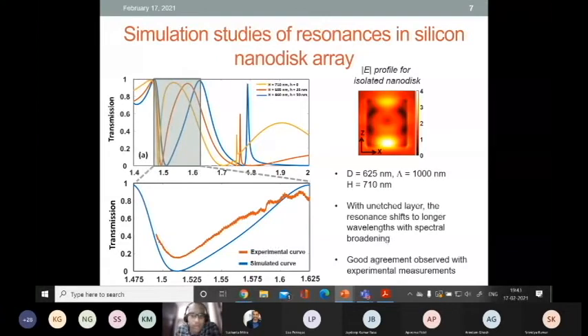This is a particular metasurface we designed, and we intentionally make these resonances broad. You can see that the full width at half maximum spans about 50 to 60 nanometers here. The reason is that our excitation light source is also broad, and we excite across a wide spectral window and also a large acceptance angle. So to accommodate the large angles of incidence and the wide spectral coverage of our laser, we make the resonances broader so that we can excite them more efficiently with the light sources we have.